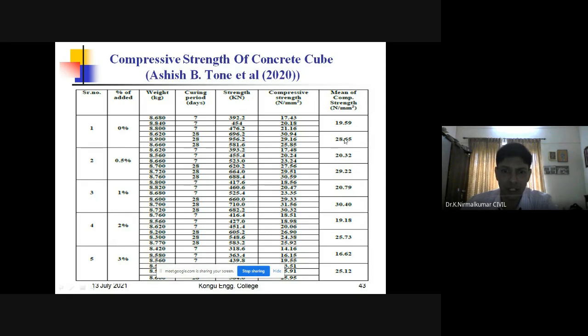It is for M20 grade of concrete. We did this experiment for M20 grade of concrete. So it was 28.55. It is really a good one. Then he went for 0.5% replacement of the e-waste with the coarse aggregate. So here, he got 29.22 Newton per mm square, which is greater than that of the conventional aggregate.